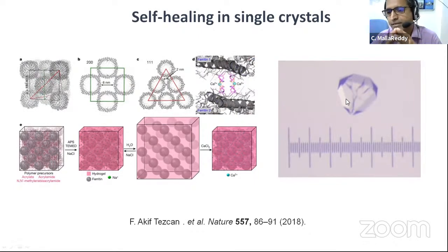When you have swelling, then there are cracks, and after some time these cracks vanish. Again, you change the concentration of the salt, then again it shrinks, and then there are cracks, and then these cracks again heal in the solution. So this is all done in solution, and with crystals in solution, you can always play around, and most of the time, because there is dissolution and then recrystallization, this always tries to eliminate the defects. Even if you cut a crystal into two halves and then put them into the solution of the compound, the crystals can actually grow the other part. So these are all known, but in solution it is understandable.